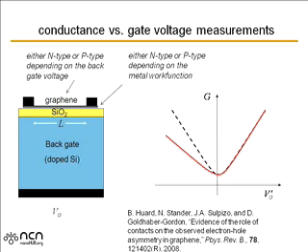So people have a couple of explanations for what this asymmetry might be caused by. It's still not something that's completely resolved, but it seems very likely that the contacts are playing an important role in these. Sometimes you see the asymmetries, sometimes you don't. Whether you see it on one side or the other might depend on what metal you use for the contacts. This is a very nice paper that I'll recommend to you. They also talk about how if you carefully do 4 probe measurements, you can eliminate these effects and always get symmetrical characteristics.